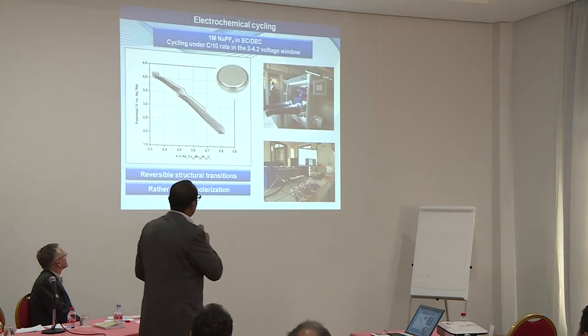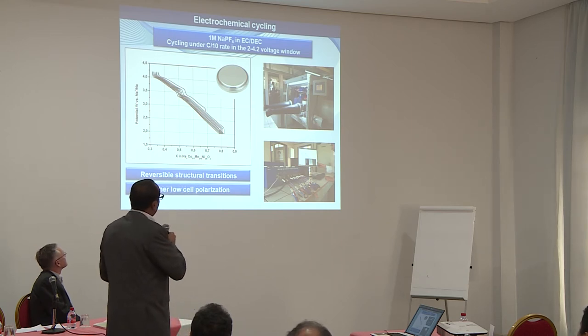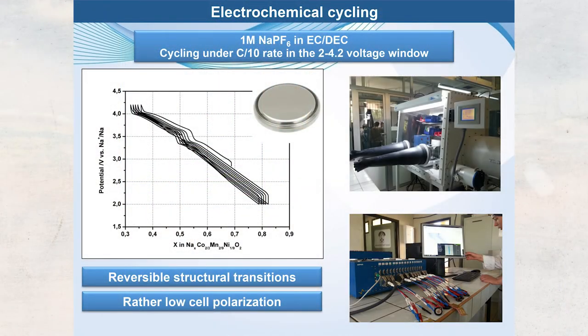These are the charge-discharge curves obtained in our lab. The electrolyte formulation is very sensitive — to water and many factors — requiring many trials. Compared to pure sodium cobalt oxide, which shows many steps, our NMC-substituted material shows only one step around 0.5 V and good reversible capacity.